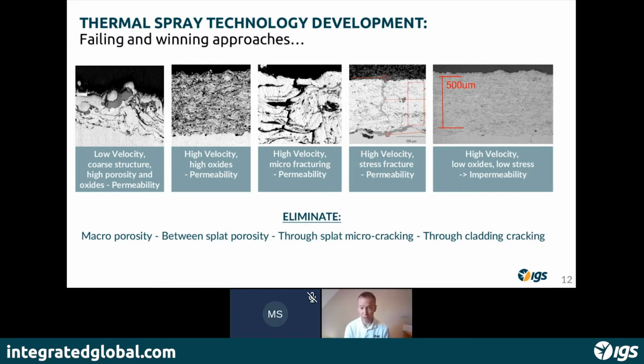We've used HVOF systems, so high velocity oxy-fuel, and these create a very dense microstructure. But if you're applying them in the field, it's very difficult to control the parameters. So if you're doing shop work with a controlled environment, robotic application, perfect. If you're in the field working in a vessel, it's almost impossible to control the parameters. And what that means, because it's a highly stressed material, is you can get macro cracking and failure and disbondment. So IGS have worked with all of these materials and experienced the difficulties of managing them in the field.